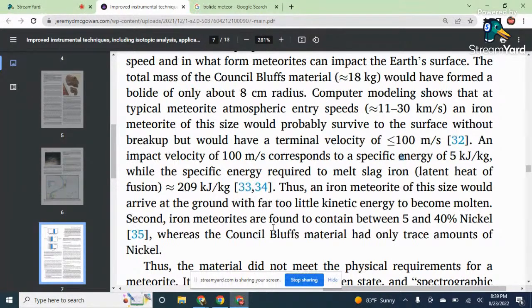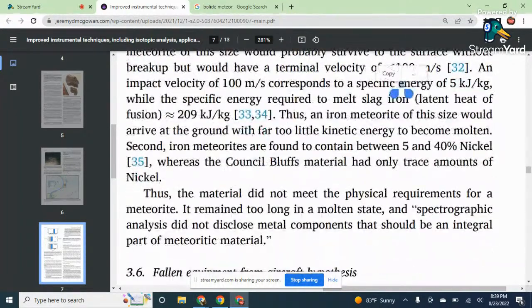So you can see 5 kilojoules by kilograms is a lot less than 209. So they're saying there's not enough energy there to melt it. Thus, an iron meteorite of this size would arrive at the ground with far too little kinetic energy to become molten or liquid. Second, iron meteorites are found to contain between 5 and 40% nickel, whereas the Council Bluffs material had only trace amounts of nickel.